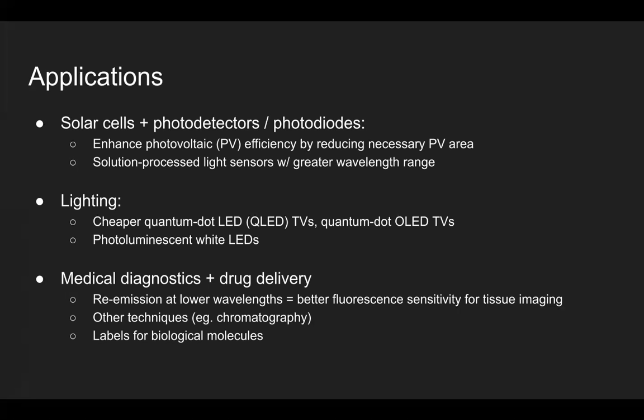The last application that I'll discuss here is biological applications. Quantum dots re-emit light at longer wavelengths that they absorb. And this allows for better separation of their fluorescence emission from the background. And this is particularly useful in imaging sensitive tissue. There's a wide variety of techniques ranging from chromatography to multi-photon microscopy that involve quantum dots and their small size, as well as the ability to modify their surfaces, makes them excellent for labeling biological molecules. However, they are made of toxic metals, such as cadmium, oftentimes. And this limits their use for biological applications, especially in humans. And so more work needs to be done in finding quantum dots that are made of non-toxic materials so that we can actually use them within tissues.